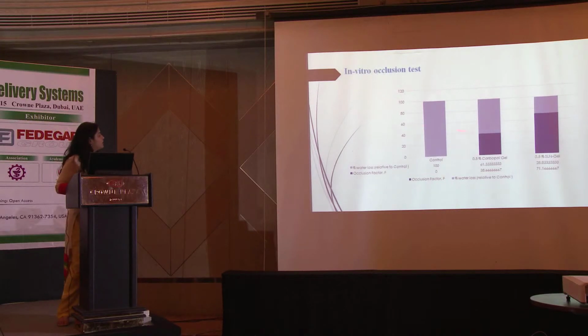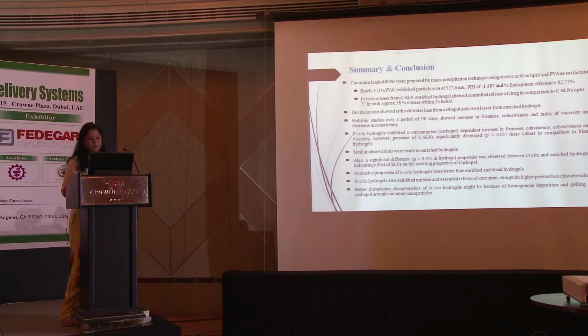The in vitro occlusion test was also performed to see what the moisture retention capacity of the gels is. The control was water. We used 0.5% carbopol hydrogel, and here this is the in situ hydrogel, and we found that the occlusive effect of the in situ hydrogel was much better in comparison to the carbopol, and this contains curcumin, which is further contributing to the film formation effect.